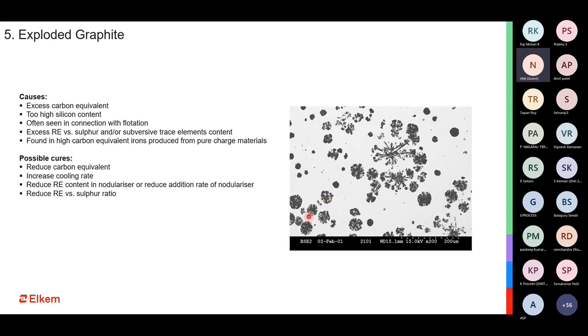So that is the exploded graphite. Why do you have exploded graphite structure? When you have a very high amount of carbon equivalent, it means your graphite nodules are big and they are not able to retain their shape.